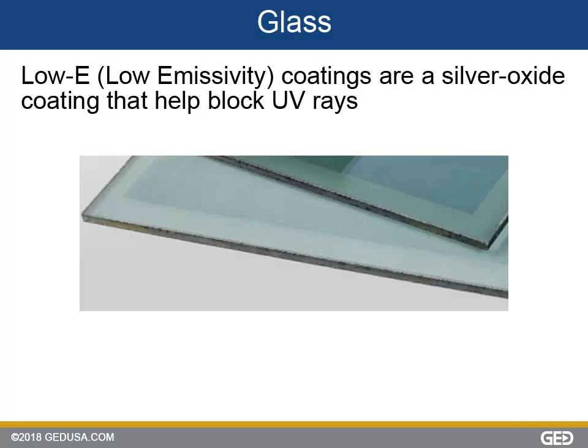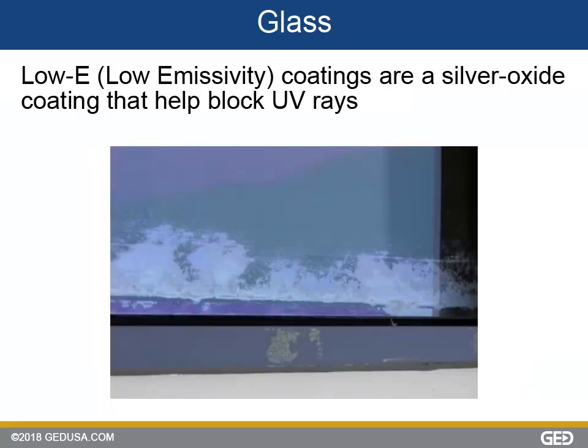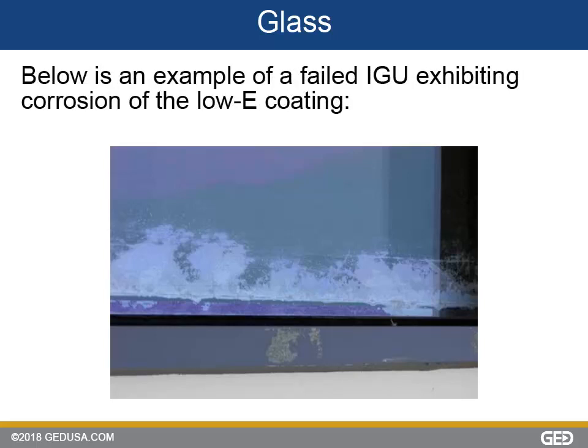Commonly, one light in an IGU is coated with a microscopic silver oxide layer that helps block UV rays from the sun. These are referred to as low E coatings, where the E stands for emissivity. Normally, as shown here, the low E coating is edge deleted from the perimeter of the light to prevent oxidation of the coating between the sealant and the glass. Oxidation of this type will cause a sealant adhesion failure, resulting in a failed IG unit.